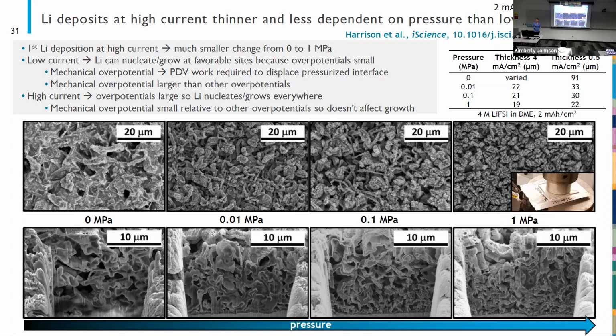Now that means that the overpotential related to mechanics and doing work to displace the interface can be a major component because we don't have a lot of overpotentials in the system. We're not kinetically limited or mass transport limited. And so that mechanical overpotential can play a huge role in where the lithium will deposit. And so that mechanical overpotential is going to dictate that we're going to start plating in these low pressure regions and even out the morphology because we just don't have a lot of other competing overpotentials.